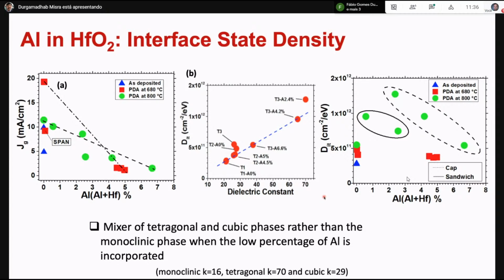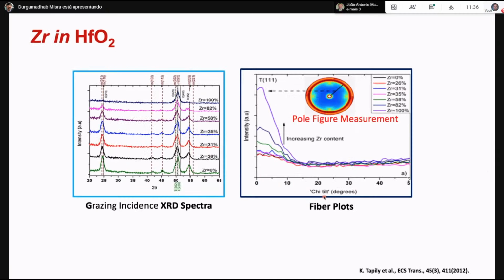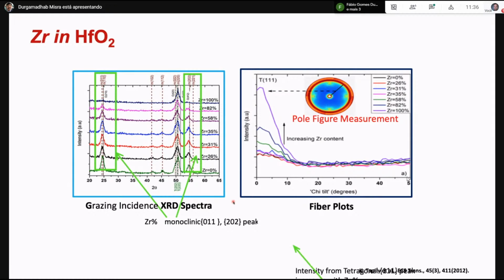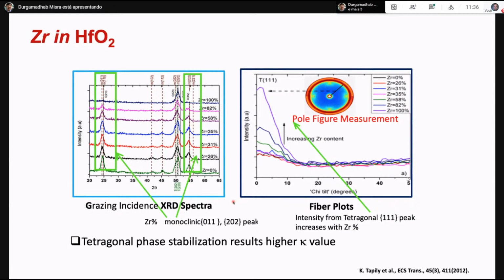Another thing I mentioned, that we can add zirconium into hafnium oxide. If you add zirconium by small percentage, for example, here is one example of 0% zirconium to 100% zirconium. If you add that one and look at the crystallinity of this film, actually this changes from monoclinic to, there is two different, this is full figure measurement as well as the GI XRD spectra. Actually, there is a tetragonal phase stabilization. Tetragonal phase is a tetragonal crystalline phase, but it results much higher high K value. So this is actually one good thing.